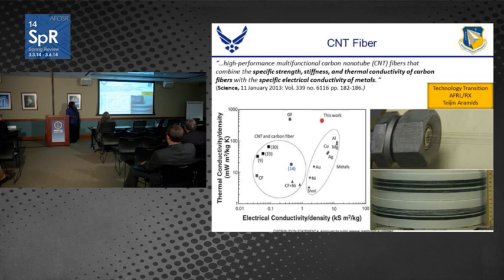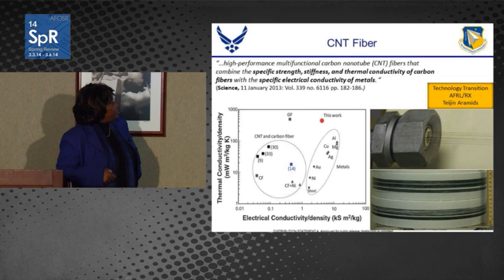And what's really nice about these fibers is they have significant advantages in terms of multifunctionality. The mechanical properties are nice, but you see here, if you look at the specific thermal conductivity versus electrical conductivity, these materials excel in both arenas. And so you have electrical conductivity on the order of traditional metals, and also very nice high thermal conductivity. And so you can see these might be useful in aerospace structures where you really want to make sure that you can get the heat out. Typically we would use something like this GF, which is a pitch-based fiber, the highest thermal conductivity material, but they've been able to make these, and this has resulted in a nice tech transfer where a company by the name of Teijin Aramid has picked up this technology and is scaling these fibers up.